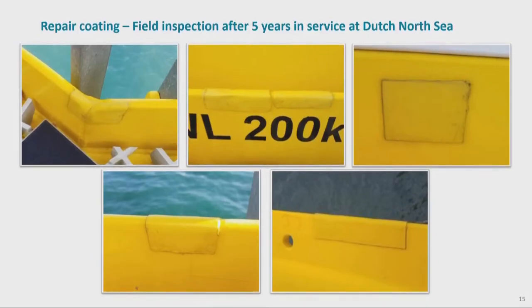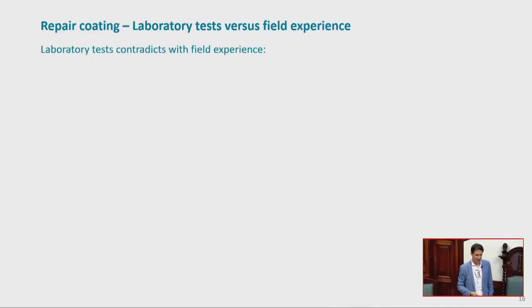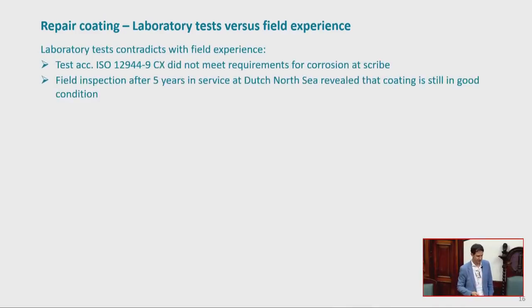And this also shows you where you use it. Every one of these points was maybe a chip of paint, some sort of damage. You wire brush it, you patch it, and that's it. It blends in with the color. Sure, you can see the adhesive collected some dust over time, so maybe it doesn't look perfect, but at least it's protecting the surface and the corrosion is not spreading. So I'll go through this part, which is laboratory tests versus field experience, and mainly we're focusing on corrosion at scribe.